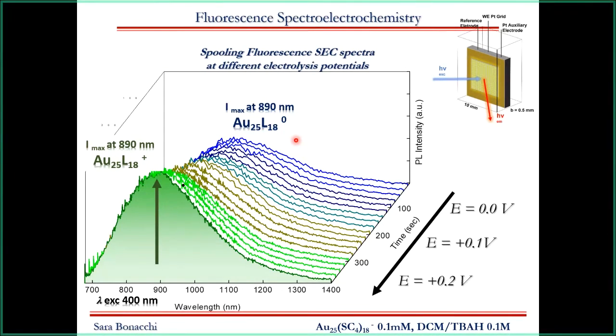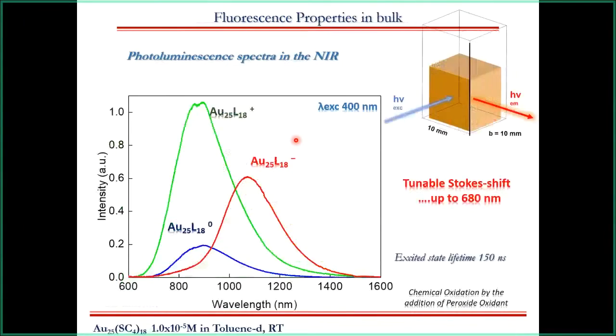To prove that these results really correspond to the three different charged gold 25 clusters, we repeated the same kind of experiment using a standard cuvette, a standard approach inside our spectrophotometer. We used a chemical oxidation to obtain the -1, 0 and plus forms, and as you can see, these photoluminescence spectra really match the ones that we obtained by means of the spectroelectrochemical setup. And this is the first proof of these three different charged gold 25 emissions.